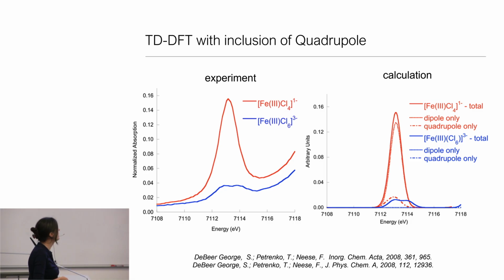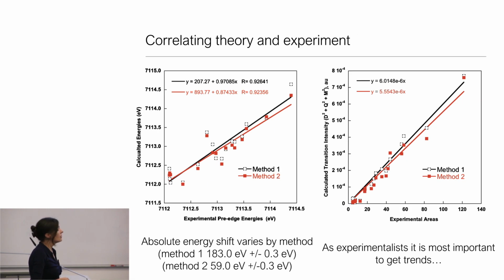Now, one of the things that I'm not highlighting is that typically to make these kinds of correlations, we don't want to just calculate and say, oh, look, ORCA can calculate my spectra. What we want to do is to use it in a predictive way and to say, hey, I have an unknown, and based on a series of knowns, based on the calculated energies and areas, can I predict what models are consistent with my data? And so what we like to do is to actually come up with these sort of calibration plots where we have experimental energies relative to calculated energies and experimental areas relative to our calculated sum of oscillator strengths.